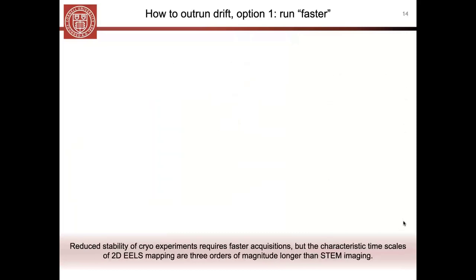Really, where that comes from is, I just showed you how you can overcome a lot of these challenges, which sounds very nice, but when it comes down to EELS, there's just this issue of time scale. If you think about your HAADF image parameters, you might take a 1K pixel squared image with something like a 1 microsecond per pixel dwell time. This is still relatively fast, especially for room temperature work, but that gives you something like a 1 second image frame, right?